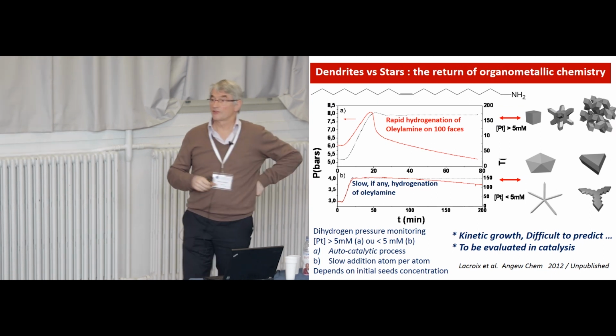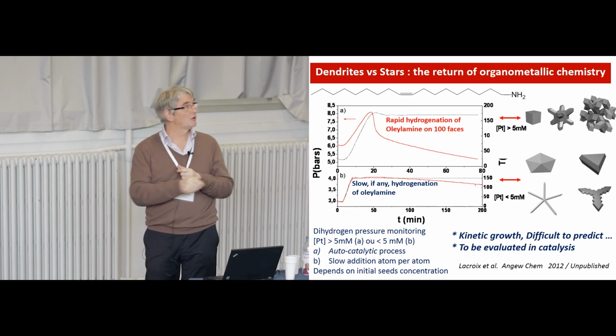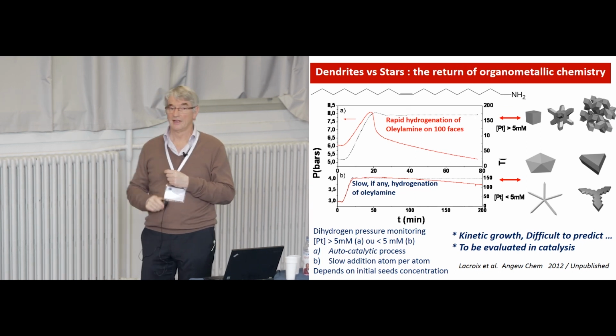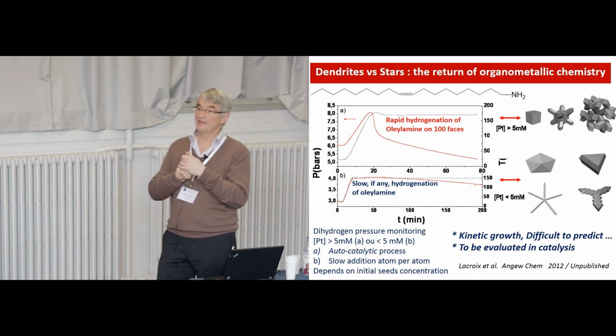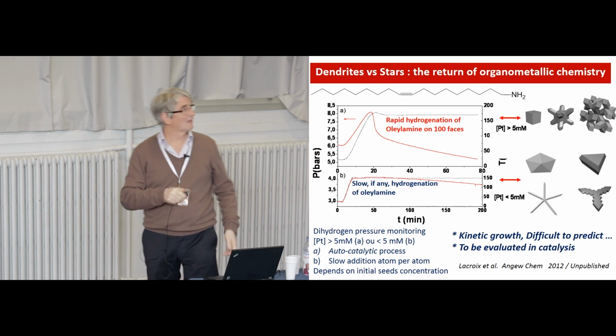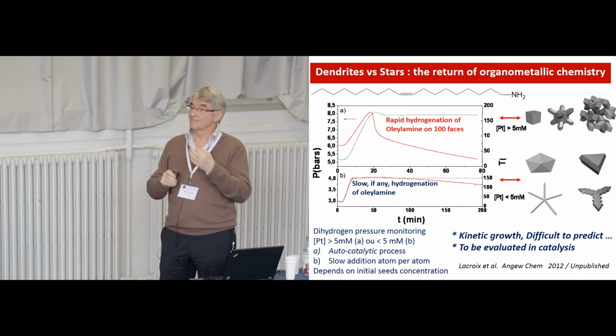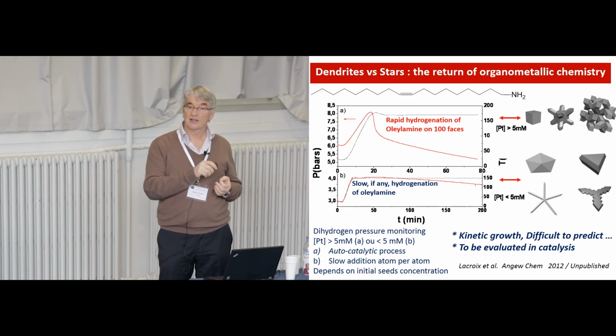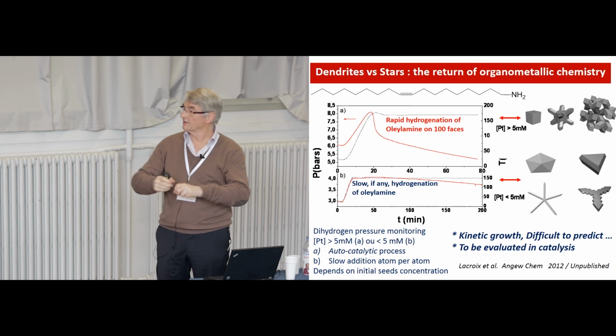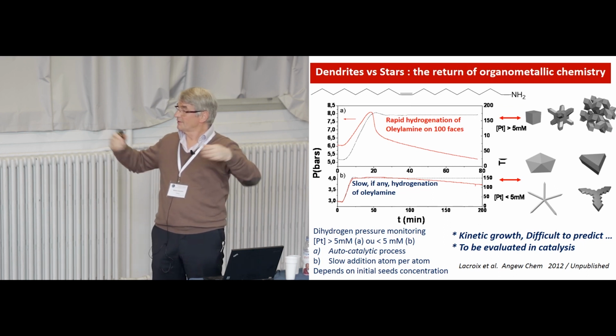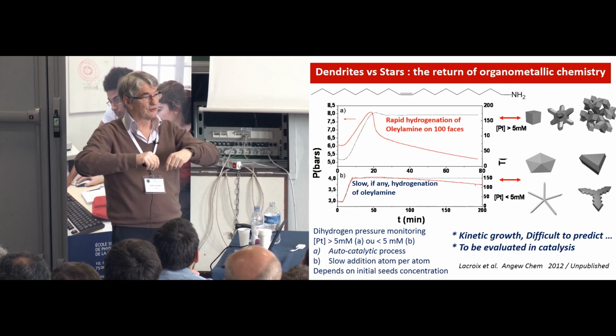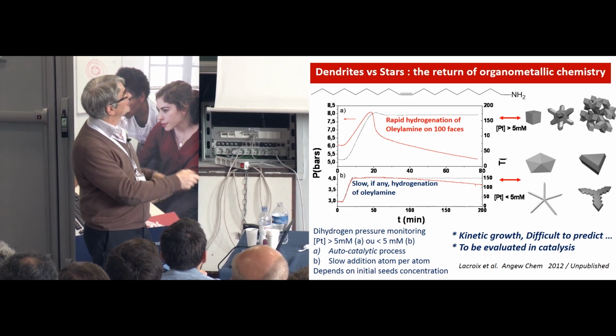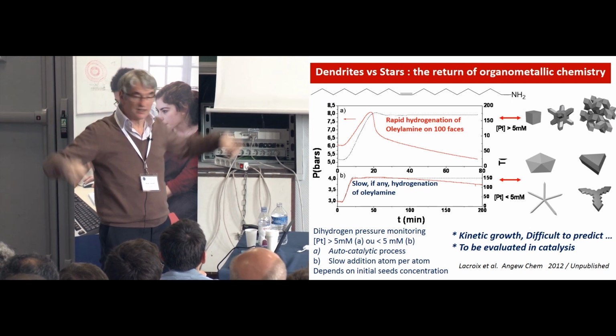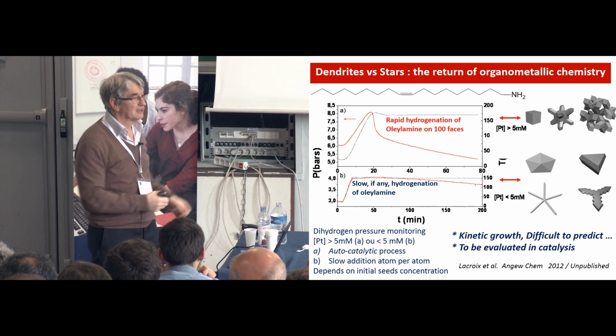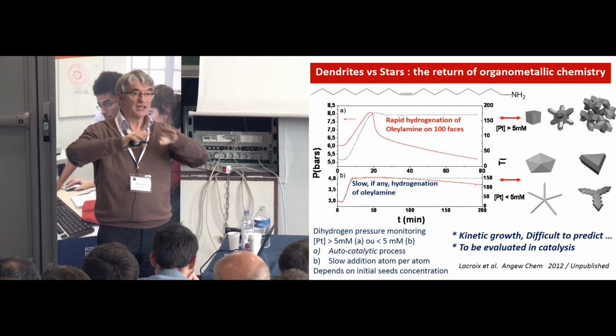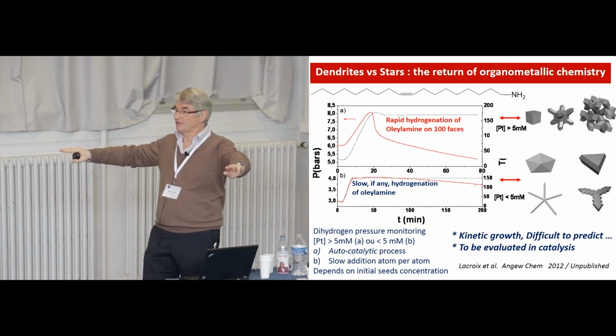Why? Because the 111 phase of platinum is not able to hydrogenate an internal olefin, and the 100 phase of platinum does hydrogenate an internal olefin. So if you have a high concentration, you make a hot spot, you start to hydrogenate the olefin, that brings heat, and then there is a burst - you bring heat to the solution by the chemical reaction. Then you get dendritic, very fast dendritic growth. If you decompose slowly, you make whatever wants to be made, and you expose 111 phases.